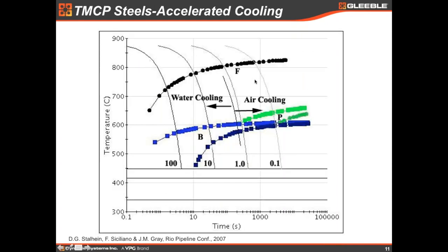Okay, this is a CCT diagram, a continuous cooling transformation diagram. Depending on the cooling rate, if it's a slow cooling rate, you have ferrite plus perlite. If it's a high cooling rate, you can have mostly bainite in the microstructure. Usually these are the typical cooling rates for line pipe steels. They lie in this range here. Then you have ferrite plus bainite. I'm talking about, of course, X65 and up